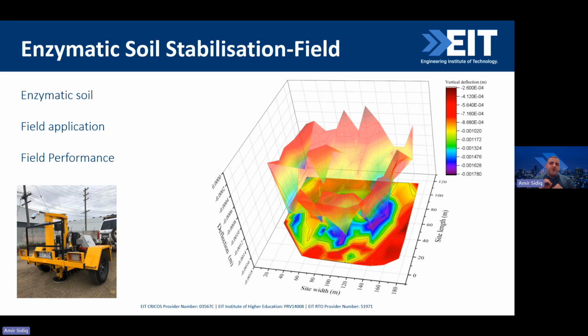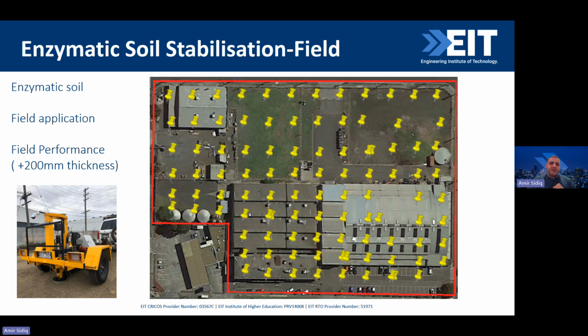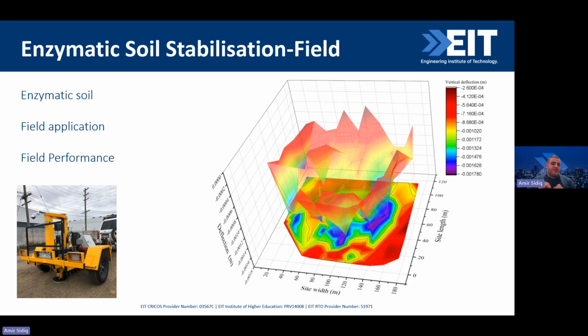I think there were only 2-3 locations across all of these locations which were about 1.6 millimeters, but the remaining were absolutely below 1.5. So just by using 200 millimeters thickness stabilization using enzyme and cement, we actually hit the target of less than 1.5 millimeters, and we're talking about 34,000 meters squared. It's quite large. And I'll tell you what is built there.